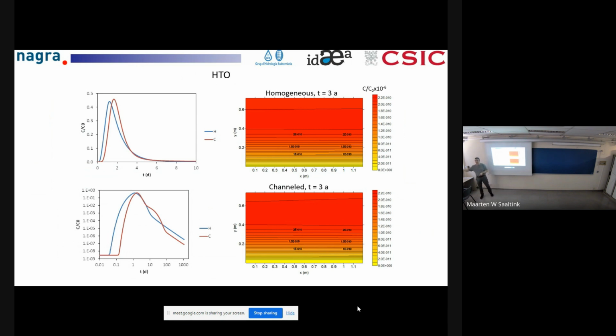So you have diffusion into the fault gouge and back diffusion from the fault gouge, which has higher porosity, high diffusion coefficient. And when you run out of that tracer in the fault gouge, then the concentration drops, and you see the second tail, which is from the rock matrix, which has a small porosity, small diffusion.